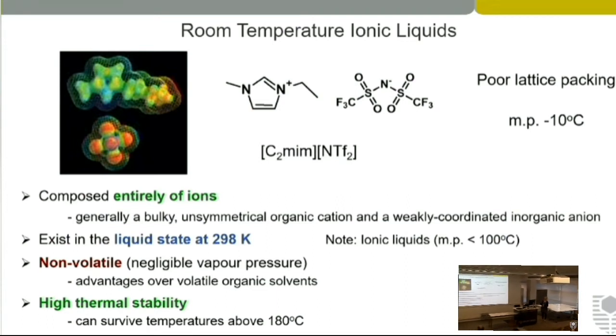As I mentioned, melting points can be changed, and room temperature ionic liquids by definition are liquid at 25 degrees Celsius. But note that you may also see a definition of an ionic liquid as having a melting point below 100 degrees Celsius. We're really interested in the ones which are liquid at room temperature, and compared to a traditional solvent, they are non-volatile. They won't evaporate, which gives us advantages, particularly in our sensors where we use very small amounts of them. They're also very thermally stable and can survive temperatures up to and above 180 degrees Celsius. So you can even perform reactions in ionic liquids at high temperatures, which you can't do in a lot of the volatile organic solvents.